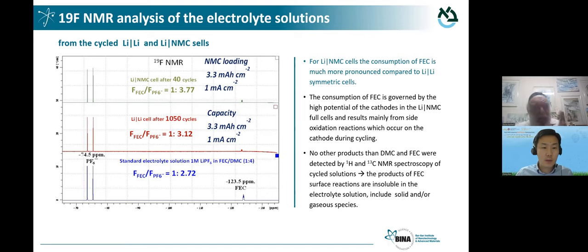And in this chart I demonstrate the effect of crosstalk. So in our cells we have electrolyte solution which contains lithium hexafluorophosphate, we have fluorine from the electrolyte, and we have fluorine from the fluorinated solvent. So we have an initial ratio, which depends on the amount of fluorinated co-solvent in the electrolyte solution. The initial ratio in our case, with 20% FEC in the solvent, is 1 to 2.72. When we cycle symmetrical lithium cells, after more than 1,000 cycles, the ratio is changing. It's 1 to 3.12, which means there was some consumption of the FEC, and thereby the relative amount of fluoride from the electrolyte was higher.